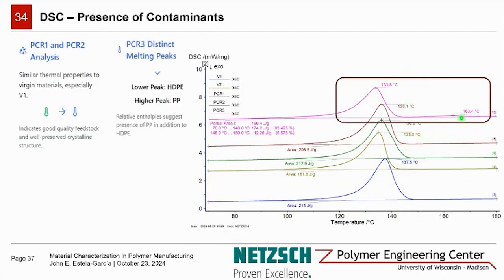There's an extra peak that's happening here, one at 134 degrees Celsius and one at 163 degrees Celsius. And this is particularly indicative of polypropylene. So this dual peak profile points to PP contamination in the recycling stream. This contamination in PCR has significant implications for processing.